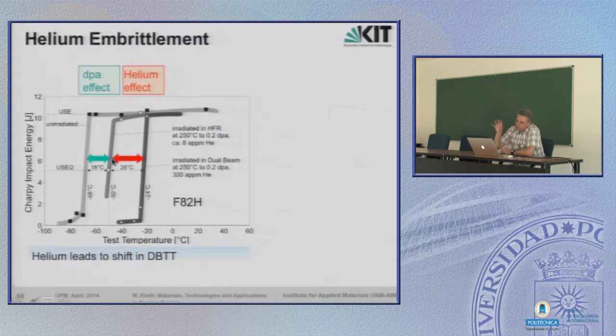And then we have included by irradiation only helium in the same specimen and see just by adding helium and by the formation of helium bubbles, you increase further the DBTT. So at first view, the effect of helium means the material embrittles in addition to all the other hardening mechanisms.